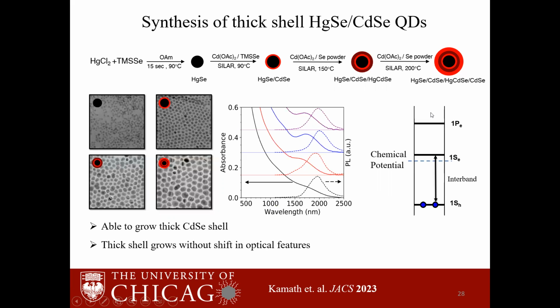One very convenient fact about mercury selenide is that the same material can be used to get mid-infrared emission as well as shortwave infrared emission. For the same quantum dots, which have a diameter of 5 nanometers, if you dope them, we get the intraband transition at 5 microns. But if they are undoped, you get the interband transition at 1.7 microns.